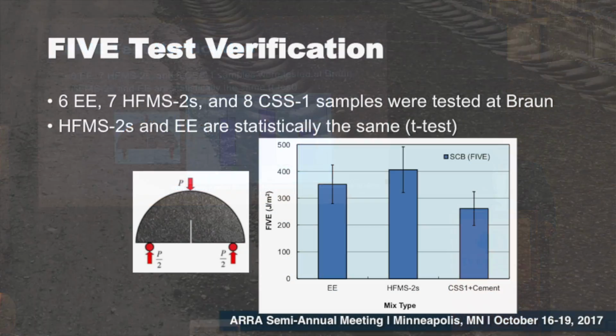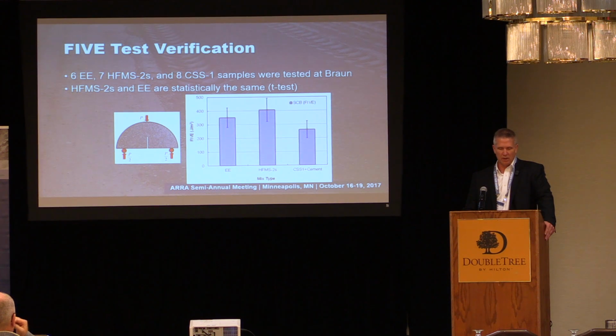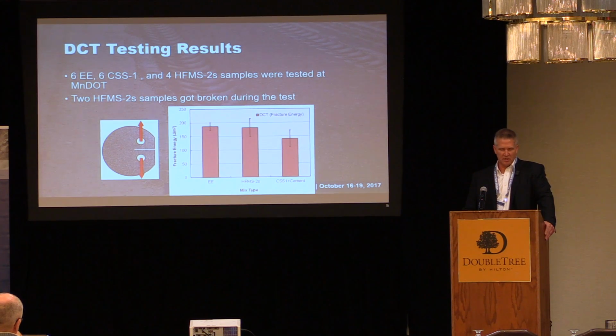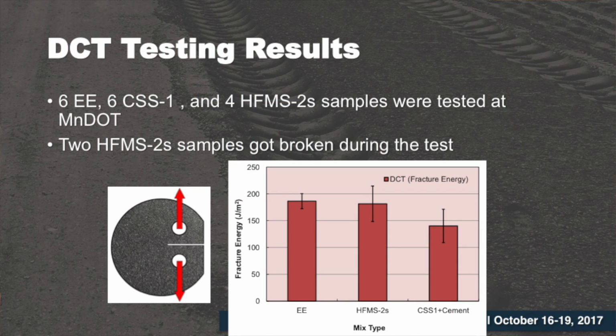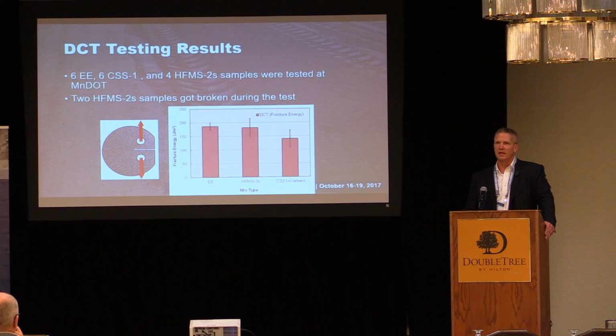So through a number of test verification steps, 6 engineered emulsion samples, 7 high float, 8 CSS1 samples, we were able to look at statistically, using the t-test, that the HFMS-2s and the EE are statistically the same in the results. So the DCT testing results also showed very good correlation. One thing that we did find, though, is that the high float samples were difficult to produce the specimens and maintain their integrity through the test, because the test specimen itself didn't have a lot of integrity to it.